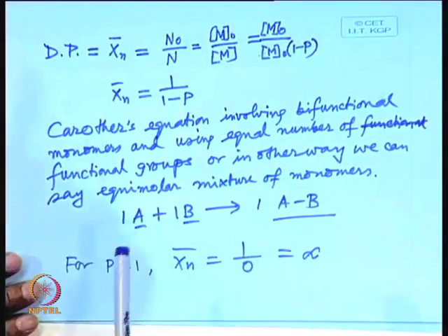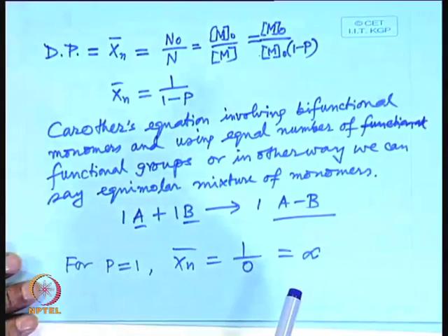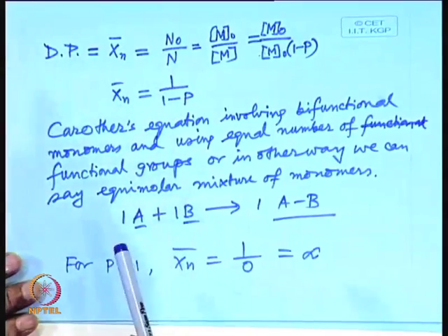You can deviate from this ideality to any other situation. So, you can have a mixture of molecules of different sizes. You can imagine the number of end groups and functional groups that will be present. Now, this gives you a clue how to monitor the growth of such a reaction. Here in this particular case, you have started with a diol and a diacid. So, you can go for estimation of alcohol or acid group by simple stoichiometric method.